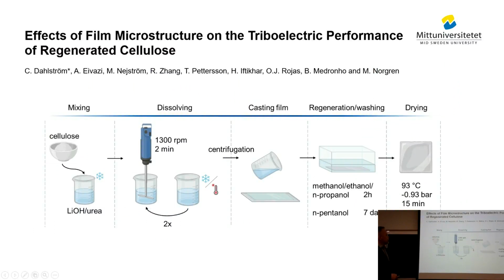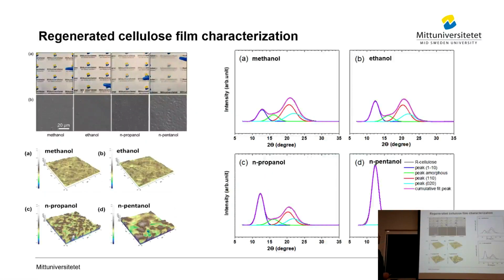Okay, so right now we're doing a job that is actually submitted and probably will go into a paper together with Orlando and also Heider at Aalto University. And we are looking at how to change the properties of the cellulose films by playing with the regeneration. So we studied a series of alcohols with different hydrocarbon chain lengths just to get some kind of systematics into it. And of course you can get films with different surface structures. You can see it gets rougher when you go to higher alcohols.